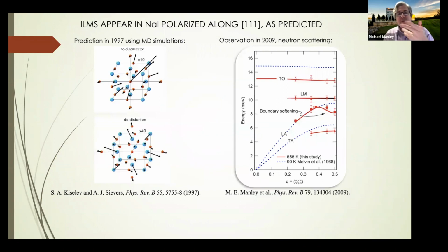So I had first observed them in uranium, but then I got in contact with Al Sievers because he had done some calculations. I said, let's look at this example. The first one we looked at after the uranium, which is where I first saw it, was sodium iodide. He had these simulations which weren't like the simulations that we do now. You started with the frozen lattice and tried to find an orientation. They do this thing called a simulated anneal, where they would create the vibration in some direction and then maybe distort the lattice until you got something that was stable. And they got a localized vibration that was stable, polarized along the 111 direction, and it came with a slight distortion of the lattice around it.